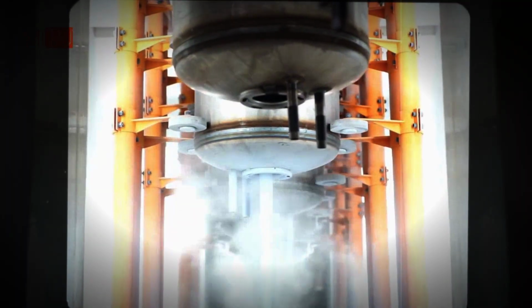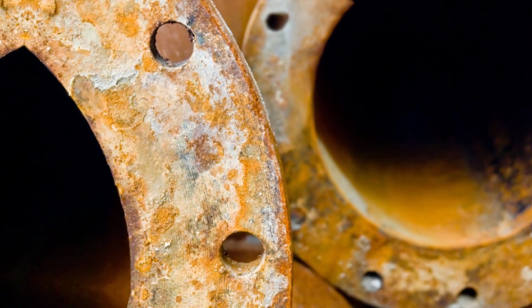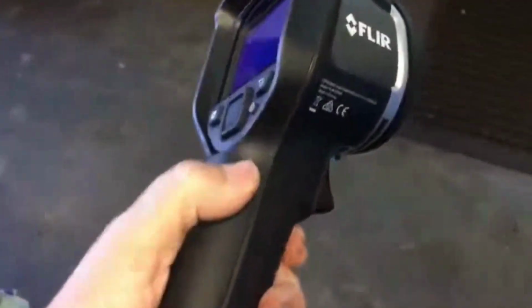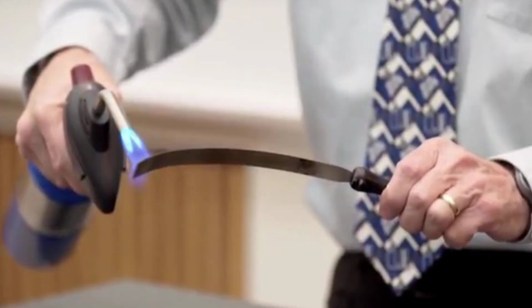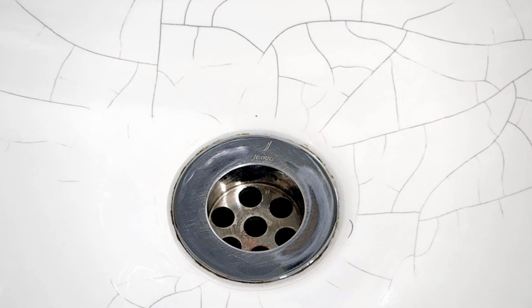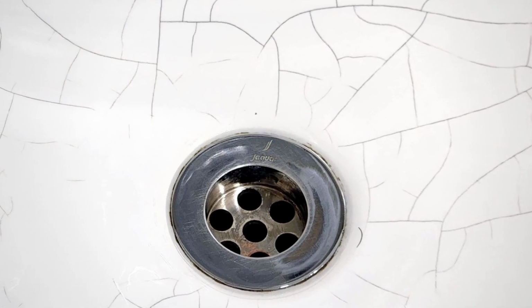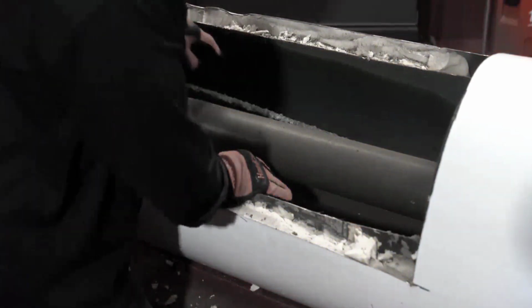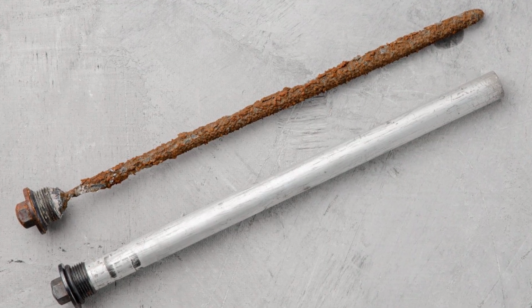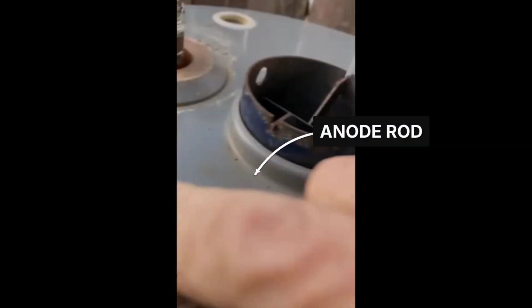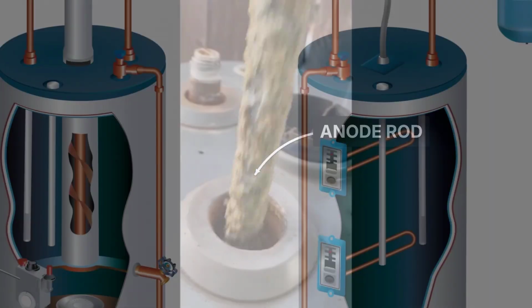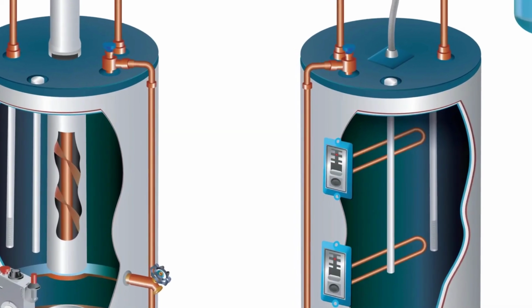Manufacturers line the inside of the tank with a thin layer of vitreous enamel, a glass coating, to slow corrosion. Yet no glass lining is flawless. Each time water heats and cools, steel and enamel expand and contract at different rates. Over time, this creates microfractures, invisible cracks that allow water and ions to reach the steel beneath. Here, the anode rod's protection is most vital. It delivers electrons to the steel exposed by these cracks, neutralizing corrosion before it can begin.